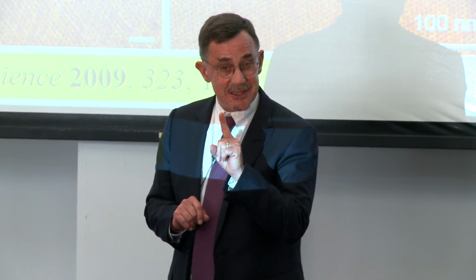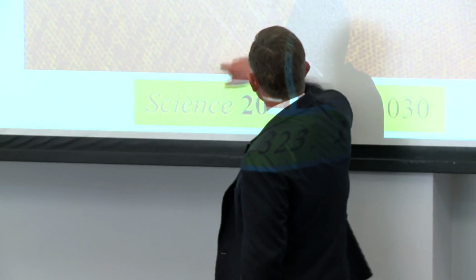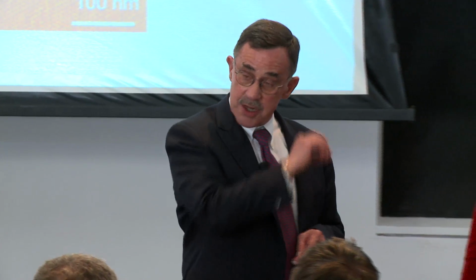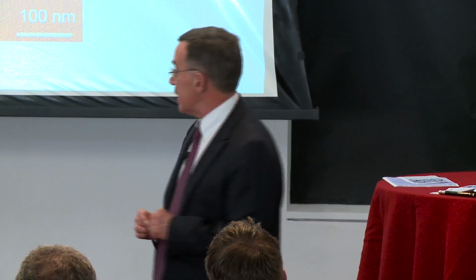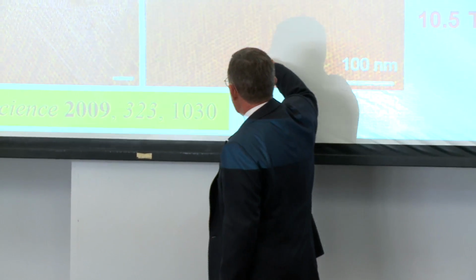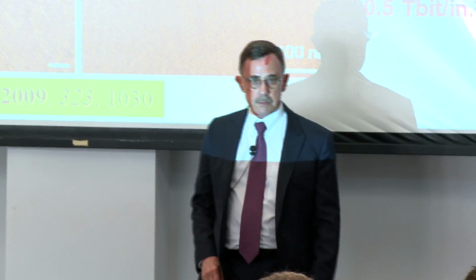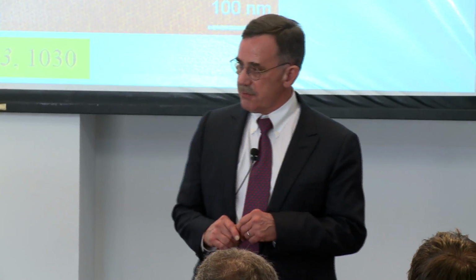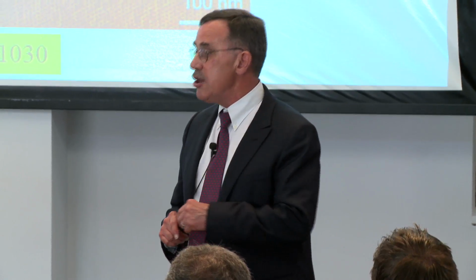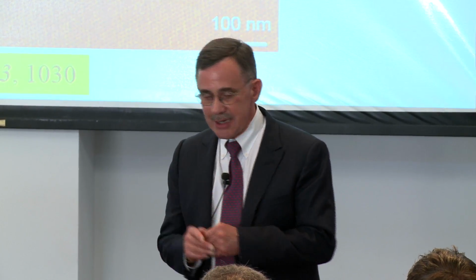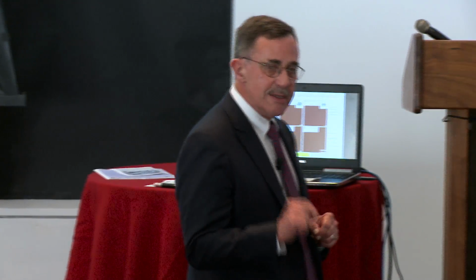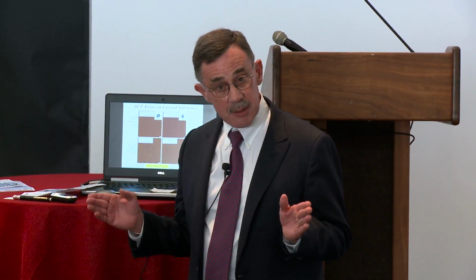That is to say, I can't tell you exactly whether I'm on a cylinder or a matrix if I were to start off here and go all the way down here. In fact, what happens is that you have a hexatic ordering, which is like a liquid-like ordering almost, along that one dimension. That's sufficient enough to cause this to be problematic. Now, I can tell you that these facets are running across the surface in one direction. So I can tell you that if we use these faceted surfaces, we can perfect the rotational ordering, but we need to have another means by which we can perfect the translational order. So we need to introduce some other force in this assembly process.